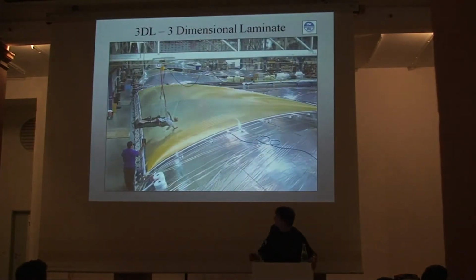Here's a look at, again, the three-dimensional laminate being made in the factory. So the silver surface is an adjustable and articulating mold, and it's just a metallized nylon cover on the mold. And you can see the sail being built full size there, and the fibers being laid down on what we call a mylar film, which is a polyester film with a thin coating of resin on top. So you can see the fiber runs corner to corner, uninterrupted, laid down in 3 dimensions.